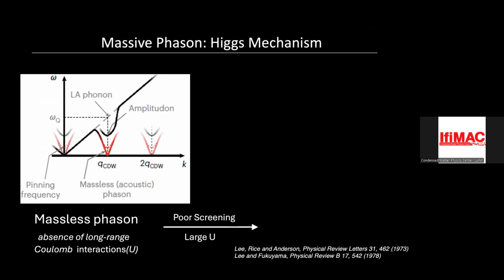What if you had a system where in the charge density wave phase, you actually had an insulator? This is not usual, but it does happen periodically. And if you have such a system, something really interesting happens. Normally, when you have a metal, because of all the electrons, Coulomb interactions are really well screened, right? So that's what a metal is. But if you have an insulator, then Coulomb interactions are no longer well screened. And that means that when a charge density wave starts oscillating, it experiences Coulomb forces due to the fact that Coulomb interactions are not well screened.